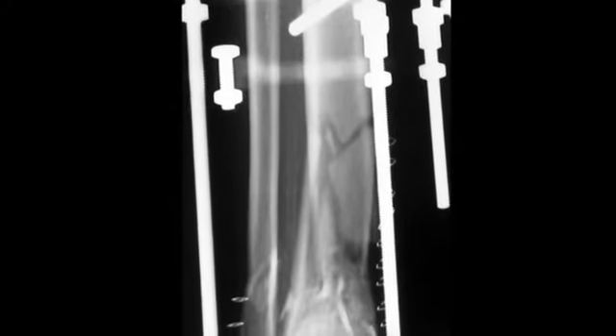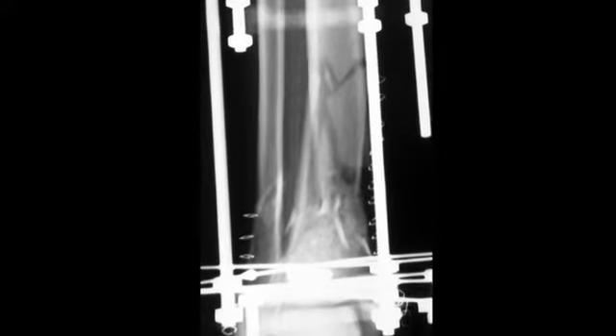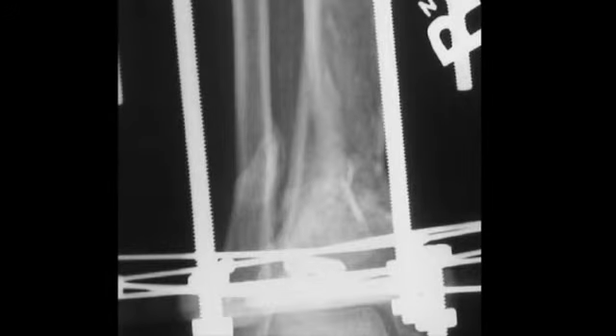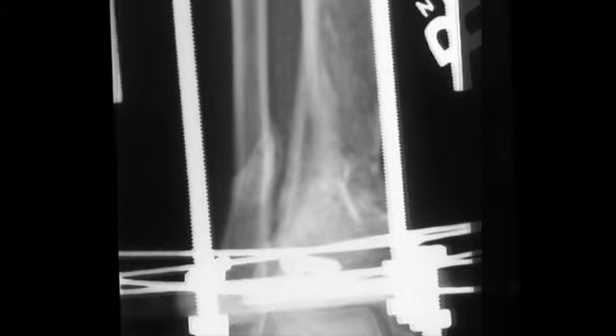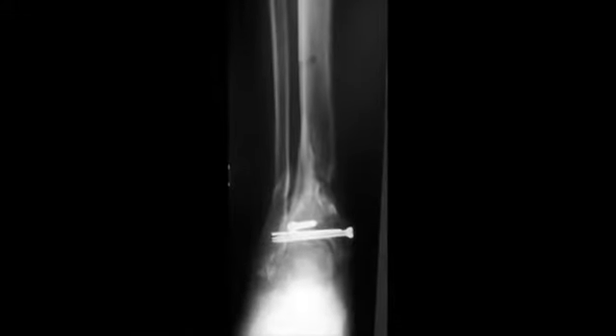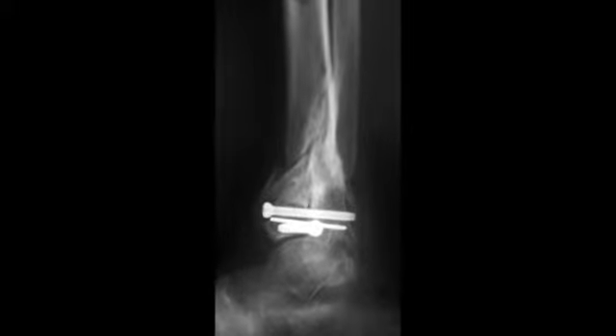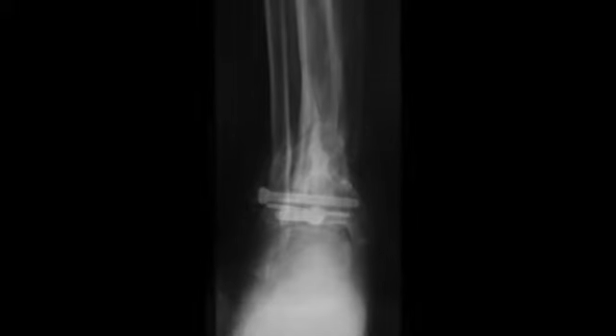Articular fixation was secured with 2 screws, and shaft fixation included an Ilizarov circular fixator. Immediate postoperative X-ray demonstrates reduction and fixation. Progressive biweekly compression of the injury site with the external fixator provided increased fragment contact and stability. X-rays at 8 and 16 weeks demonstrate consolidating fracture sites. The fractures were healed radiographically and clinically, and the fixator was removed at 20 weeks.